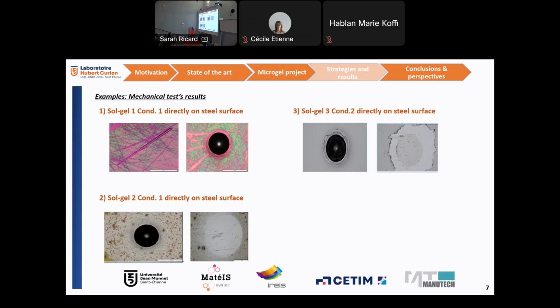When you are using sol 2, condition 1, again on these steel surfaces, you can see that our sol coating is totally removed. It means that this gray color is the steel. We removed totally this sol coating, and for this calotest, you cannot see anything because we don't have a defined mark showing that we have different thickness between the metallic substrate and the sol. And for sol 3, the same, the delamination close to this area and no well-defined calotest. So it means that after these bad results, when you are using this sol directly on the metallic surfaces in this project, we should think of a different strategy to enhance it.